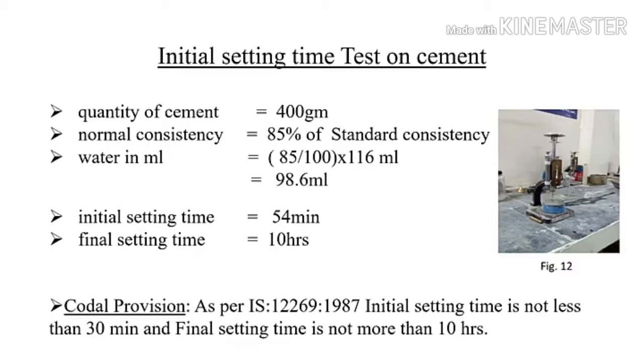Initial setting time test on cement. Quantity of cement was 400 gram. Water found out to be 98.6 ml. Initial setting time found to be 54 minutes. Final setting time was found to be 10 hours. Codal provision was followed as per IS 12269 1987. Initial setting time is not less than 30 minutes and final setting time is not more than 10 hours.